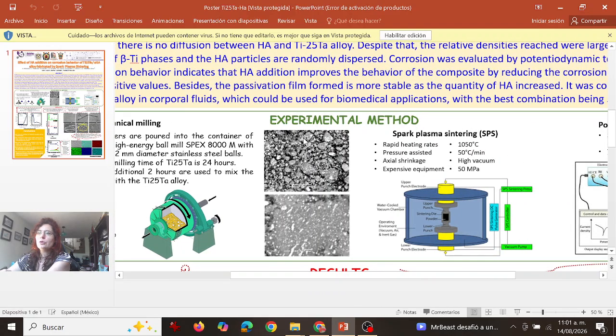Now let's continue with the sintering step. As we mentioned, we use Spark Plasma Sintering, SPS. Here we have a picture of the SPS machine. Some of the characteristics of this machine are the rapid heating rates, the fact that it's pressure assisted, and that we have axial shrinkage. We should mention this is expensive equipment. Now let's have a look at some of the parameters we used for our sintering. It was under a temperature of 1050 degrees Celsius with a 50 degrees Celsius per minute heating rate, under a high vacuum atmosphere and a pressure of 50 megapascals.